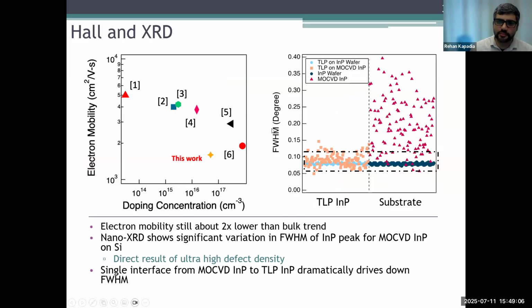However, it's still not perfect, and this is one of the things that we can see here. If we had this as bulk, I would have expected the mobility to be on the order of around 3000-ish. But here our mobility is on the order of about, say, 1600-ish. And so we're still about 2x lower than we would like to be. But essentially, this is a very promising and interesting result.